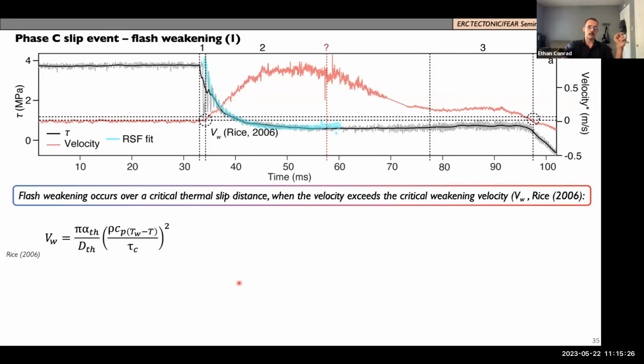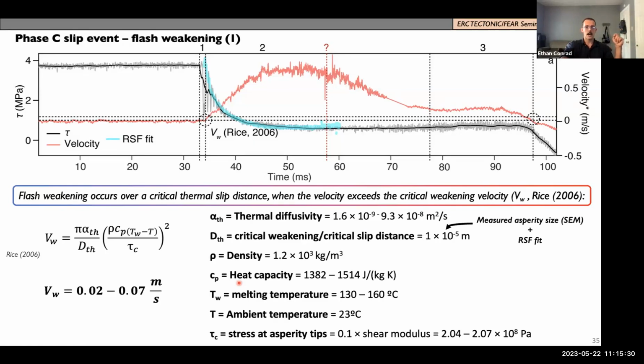And the formula for that weakening velocity is shown here, also coming from Rice. And then here's all the numbers that we use to calculate that weakening velocity. The thermal weakening distance we used from the measured asperity size, as well as is used in the rate and state fit, so it fits pretty well. And then the shear stress at the asperity tips is around 10% of the shear modulus, and that's coming from Dieterich and Kilgore. Maybe the reference is on a different animation.